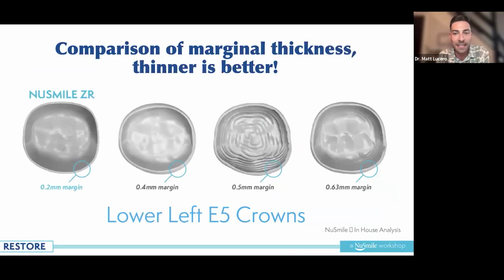And here's that difference in the intaglios. You can see the NuSmile on the left. The other three are just other manufacturers in no particular order. But you can see that the margin's a little bit thicker on those other crowns. And you can see kind of those grooves on those last two especially. They put these retention grooves on the intaglio surface as well.